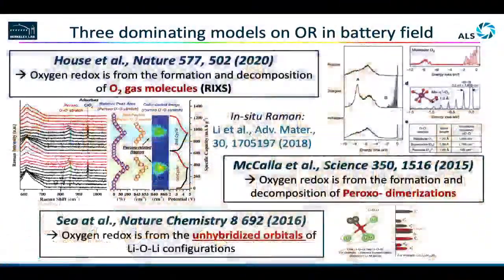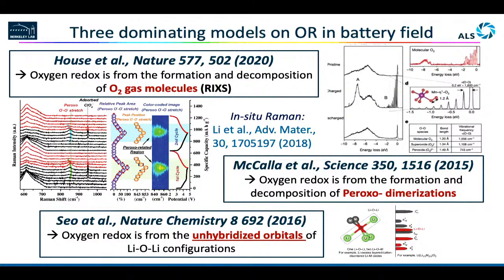The issue with this model, which I think is a beautiful model focusing on the local structure, is that it does not touch the point of what kind of oxygen after oxidization could be reduced. This could be well oxidized with oxygen release, zero reversibility, and of no use.